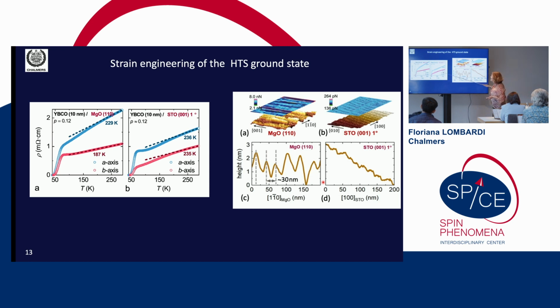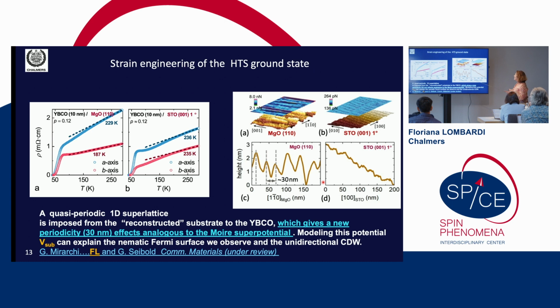And because of this, if you take a resistive transition of 10 nanometer films on strontium titanate, the same doping, what you get is that there is slight anisotropy here, because you still have the chains, but the slopes are the same along A and B. So this tells us that you have tiny variations of the properties of the films because of this step. Instead, here you are completely changing the property of the materials. But then, considering this periodicity here, you get one-dimensional periodic superlattice that is imposed on the YBCO. So the physics that you get is essentially analogous to imposing a Moiré superpotential on these films.